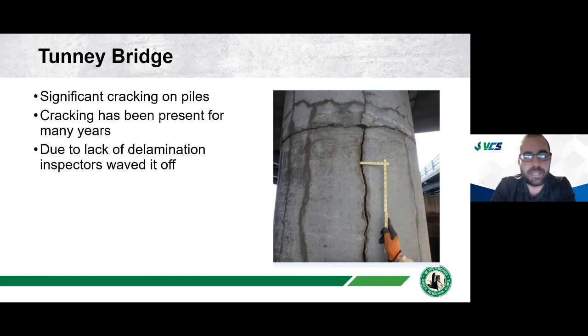So if they only see cracks, to them it's, okay, well, corrosion hasn't progressed too far. We're just seeing cracks. There's no delamination. It's fine. And so for many years, this bridge was left like this with these very large vertical cracks in the piles because there was no associated delamination. Then the contract for bridge inspection changed engineering firms, and I had a very good relationship with the new firm. They did their inspection, saw these cracks, and alarm bells went up for them. They called me and said, Brian, we saw these cracks, but there's no delaminations. Are you concerned?